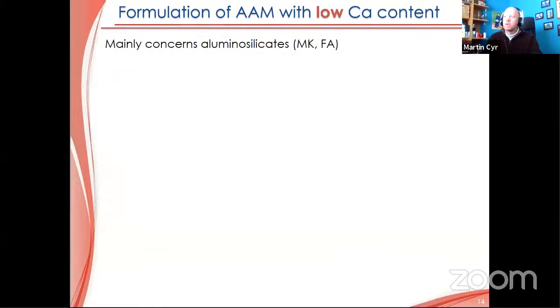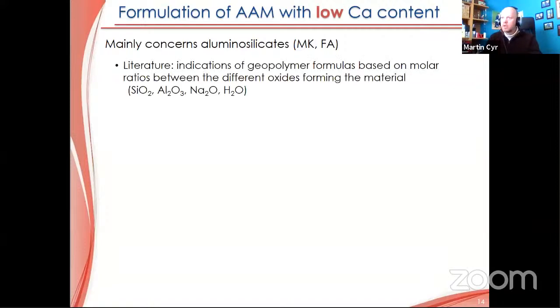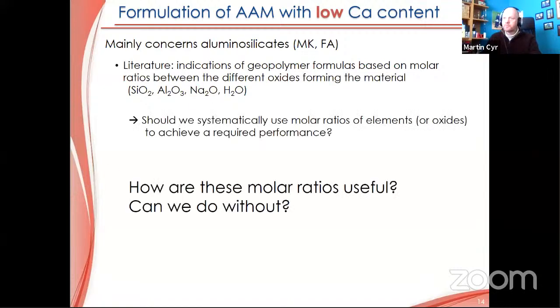So if I have a look now at low calcium content, mainly metakaolin here, because we don't work too much with fly ash in France because we don't have it anymore anyway. The literature is saying that we should use some molar ratio between the different oxides forming the material, silicon, aluminum, sodium, and also water. And a question we have a lot: should we systematically use these molar ratios of elements to achieve a required performance? Are these molar ratios useful? Can we do without? That's really a big question we have very often. And we are trying to work on this.